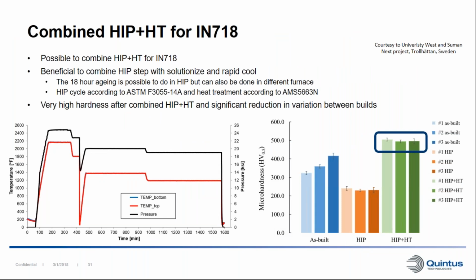If we look into Inconel 718, which is a popular material, we have done trials for high pressure heat treatment of this as well. It's very possible to combine the conventional HIP cycle with the conventional heat treatment according to ASTM F3055 and AMS 5663.